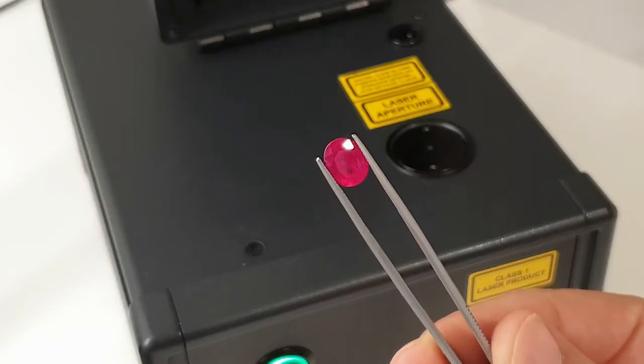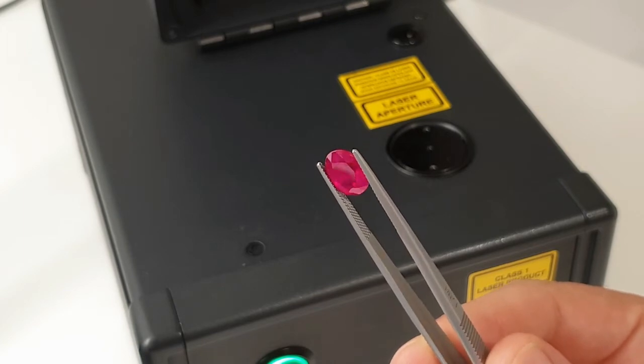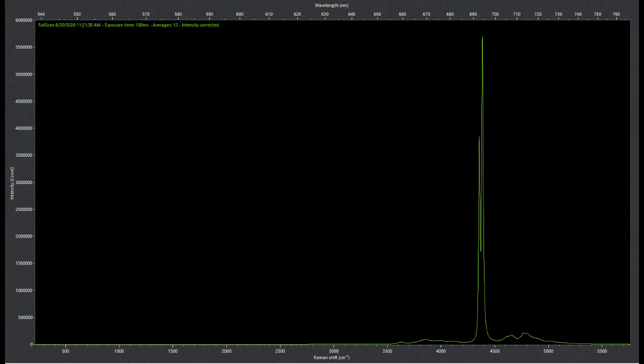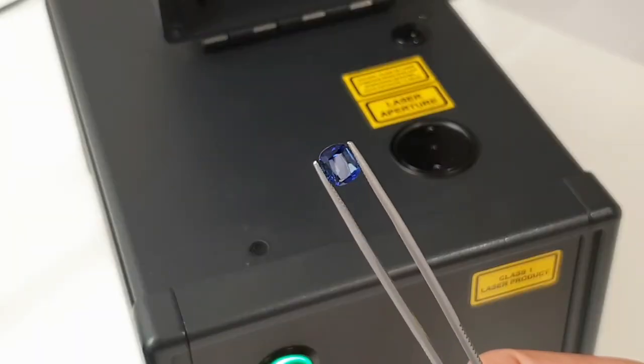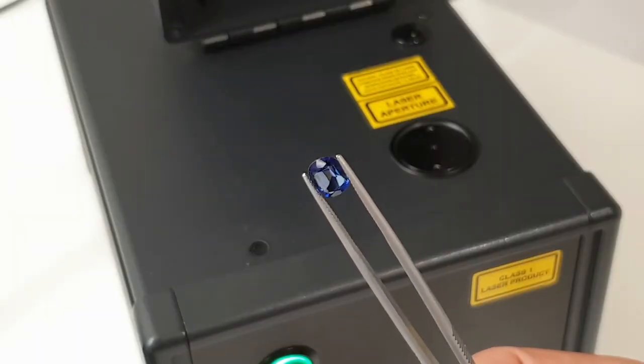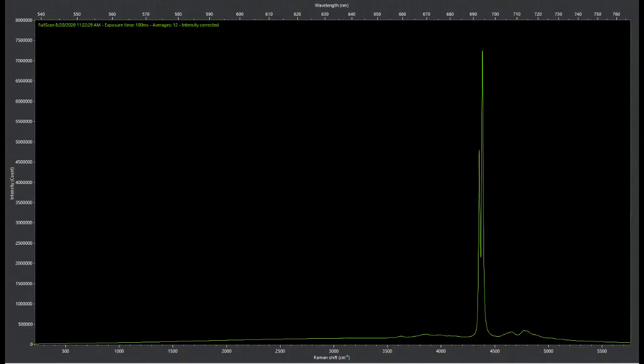This chromophore element is common in stones like ruby, sapphire, emerald, spinel, alexandrite, and many others. Even a minimum quantity of chromium can trigger a PL reaction that can make the Raman signal practically impossible to be seen by the spectrometer.